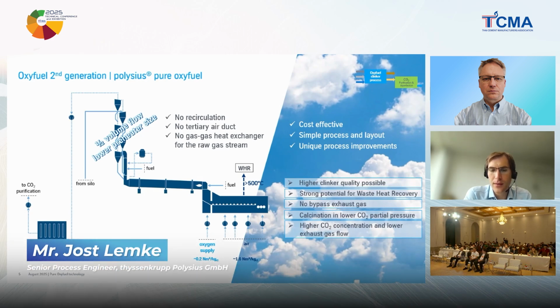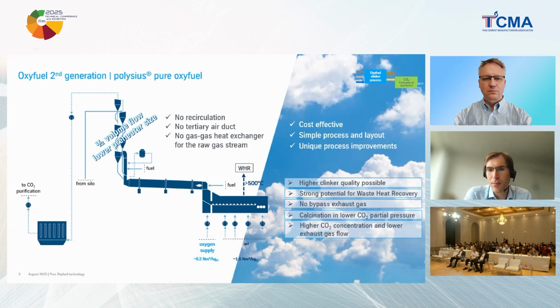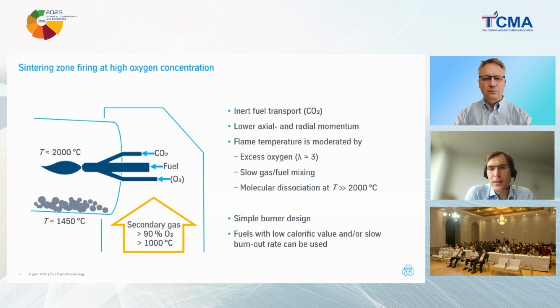And the changed atmosphere in the sintering zone also bears the potential to produce even higher clinker quality in the future. Furthermore, there's a strong potential for waste heat recovery due to the elevated cooler vent air temperature, which is in the range around 450 to 500 degrees C. That allows a good temperature level for the waste heat recovery and power generation.